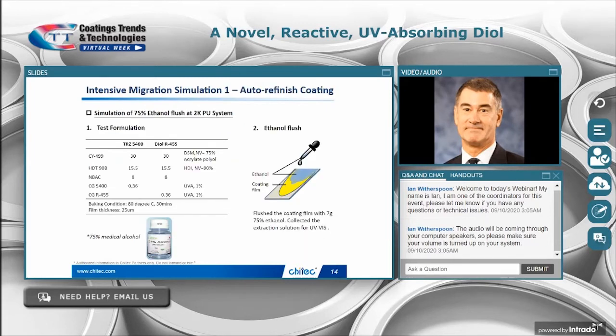Okay. In this next test, we are using a much less aggressive method to extract the film. It's a water-ethanol mix. Might not be too different than windshield washer fluid, something like that. And this should give us a better feel for whether or not mild aggravators can extract the UVA. In this case, we drip the solvent onto the surface, wash down the panel, and for a control, we chose our best non-reactable UVA, the 5400 triazine, for comparison purposes.